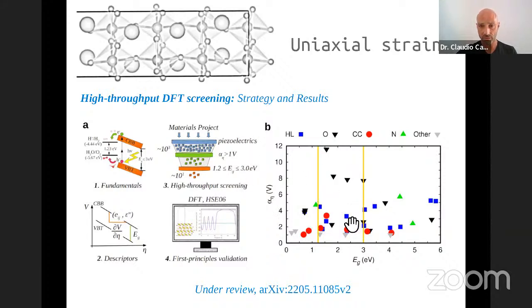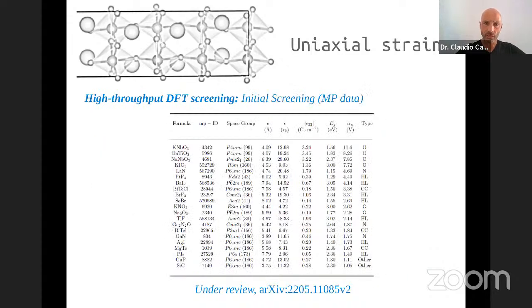So those 20 are those shown here that now I will show in a table, right? So these materials here entail some halides, oxides, chalcogenides, nitrides, and other semiconductor materials, right? In principle, according to our high throughput screening conditions, they are optimal for these piezo-photocatalytic applications, right? So here are those around 21 materials that we sieved. Okay, so we found barium titanate among the best performing.